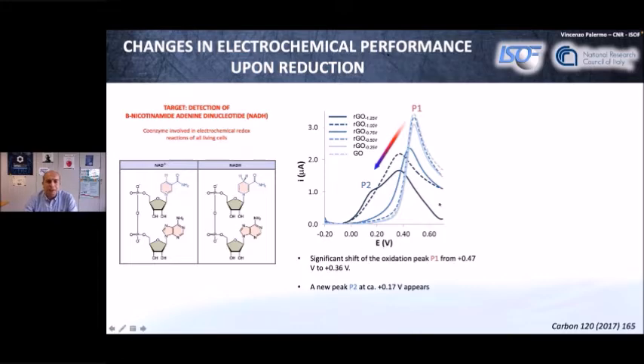So here you see the response of the electrodes tuned at different positive voltages. And these are different electrodes that were reduced to different degrees. So you see graphene oxide, as deposited, and then reduced graphene oxide, reduced at different potentials. You can see that there is a significant change. When you use more and more reduced graphene oxide electrodes, you see that there is a P1 peak that then decreases and shifts a bit, and then there is also formation of a second peak.